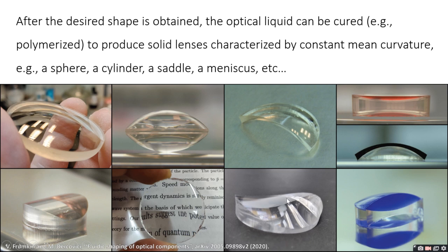This lens is made in a way similar to the cylindrical lens, but with a different volume of the optical liquid. Lastly, you can see a doublet lens, where a concave lens was first created and then used as a bounding frame for a convex lens made out of another polymer with a different refractive index. Here, the other polymer is dyed blue for visualization.